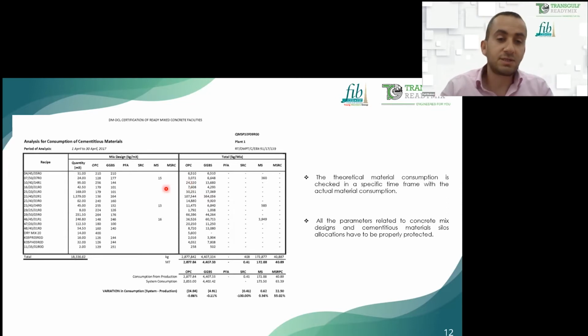The operating system of the batching plant generates the mix design production. In this mix design production, we can get mix codes and how much quantity is produced from each code. And as per the approved mix designs, we can get the theoretical consumption. As an example, this mix contains 420 total cement. We have 210 OPC and 210 GGBS. Produce 31 cubic meters. So 210 kg times 31 is 6,510, and 6,510 for GGBS. This is carried out for all the mixes, and we get the theoretical consumption from this.